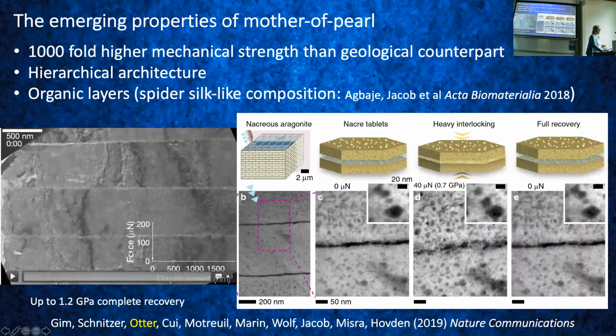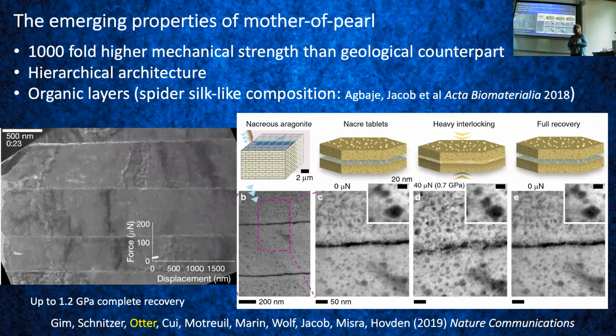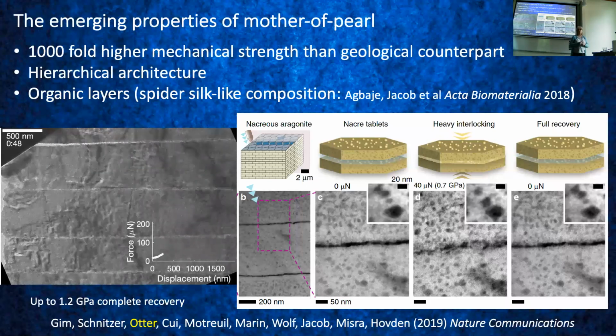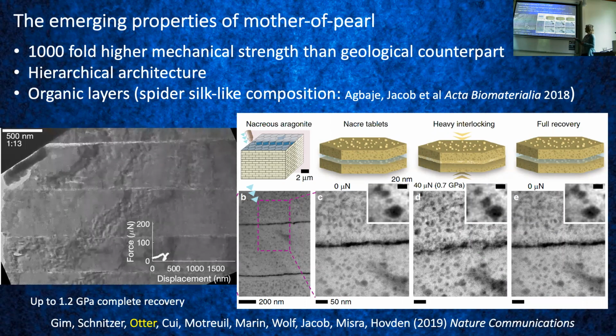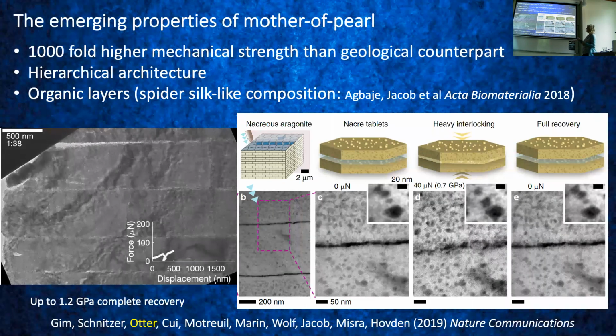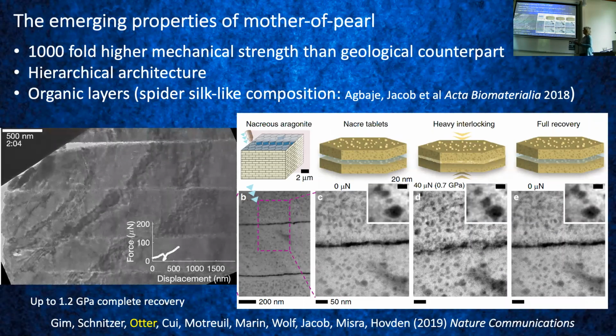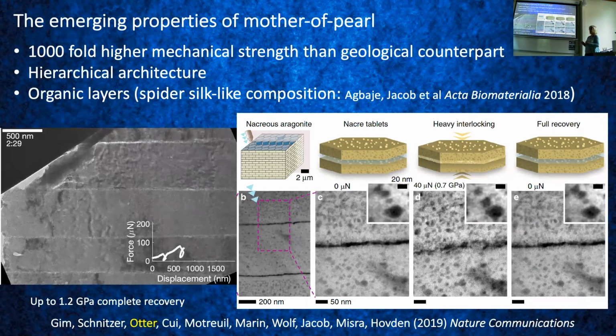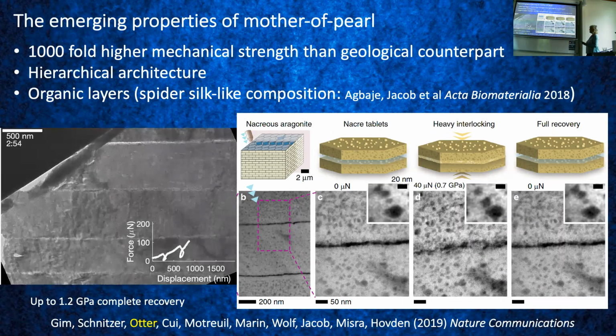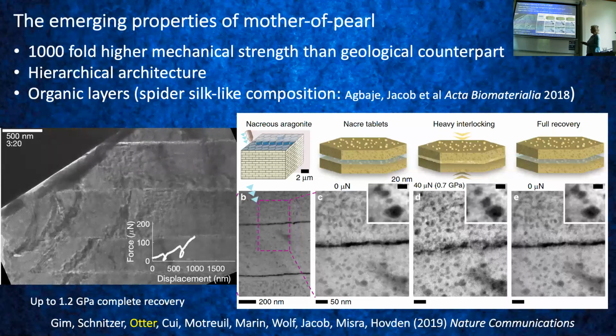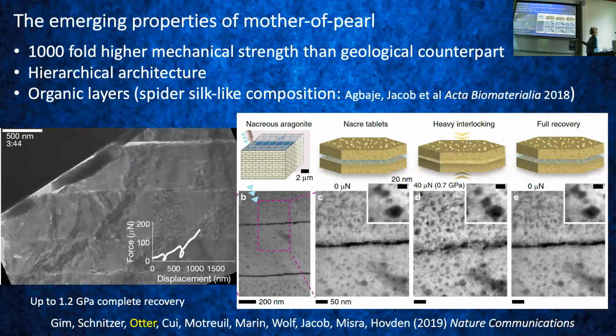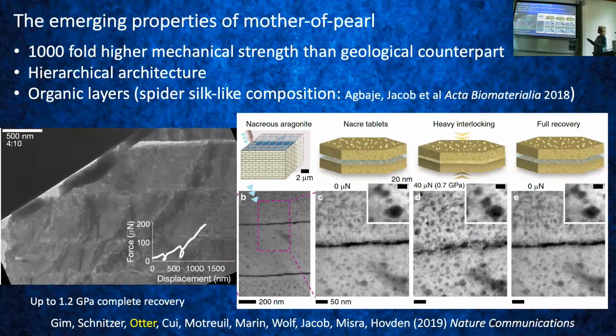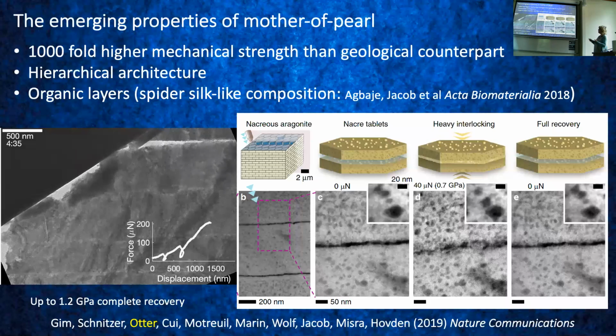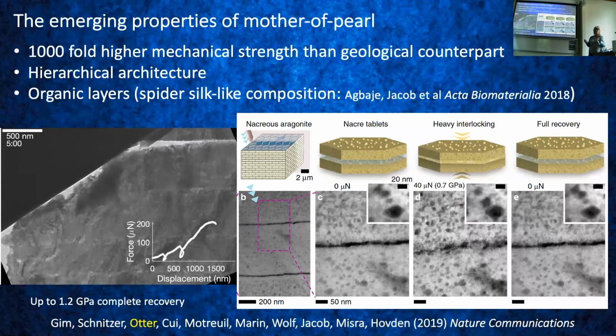We were then involved, actually with my postdoc, then PhD student Laura Otter, who worked with a group of material scientists doing nano indentation in the transmission electron microscope, which is schematically shown here. This is the load change here, and what you can perhaps see is that the pressure increases, and we went up to 1.2 gigapascal before the tablet breaks, but up to 1.2 we can see complete recovery. So they were smashed together, but if you release the pressure before you come to the break point, you get a full recovery. It all looks like before.